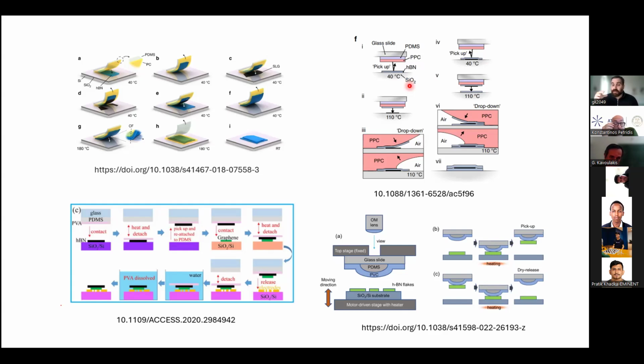You use this temperature to go down and come in contact with your heterostructure or your flake. You pick it up at 40 degrees because you have to drop the temperature to the limit in order for this to be more solid and pick up the flake without staying down. And then you put everything down at higher temperatures. Now, the temperature that they report here is 110 degrees. I am not using that one because it's dangerous for twist angle relaxation, and also it's dangerous to leave everything down and then have to use chloroform again to dissolve. What I use is 75 degrees, and it is working pretty well.